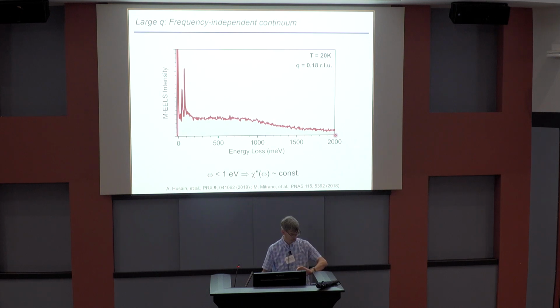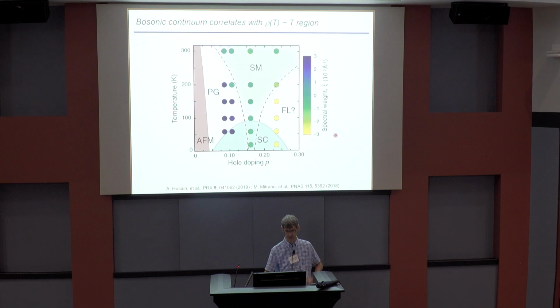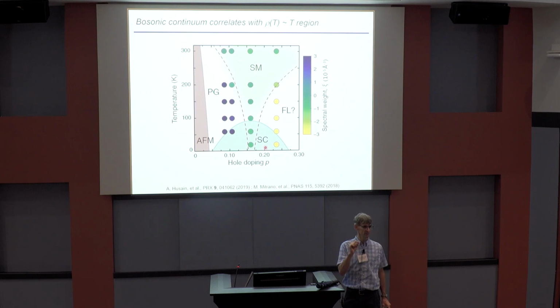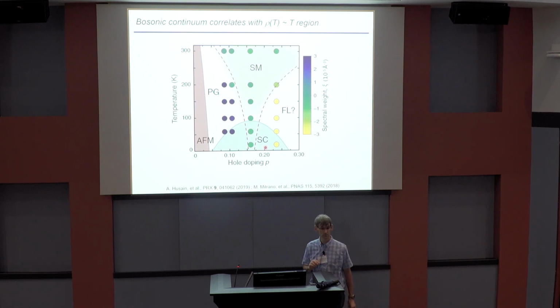So the relevance to strange metals comes when you ask, what part of the phase diagram has this continuum? This was published by my student Ali Hussein in 2019, but it basically lives inside a fan region of the phase diagram that's centered on optimal doping. So there is a perfect correlation between a T-linear term in the resistivity and the existence of this continuum. Now, correlation does not imply causation. They could exist for completely different reasons, but when one is there, the other one is too.